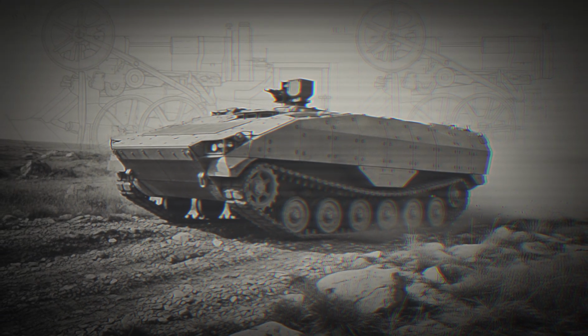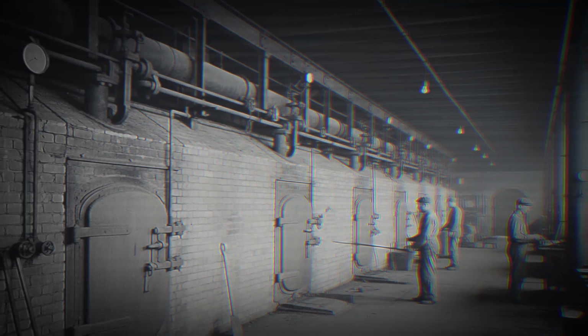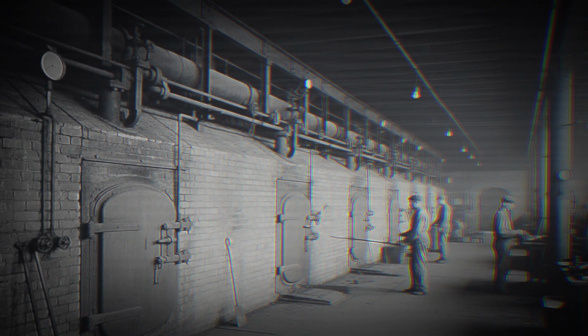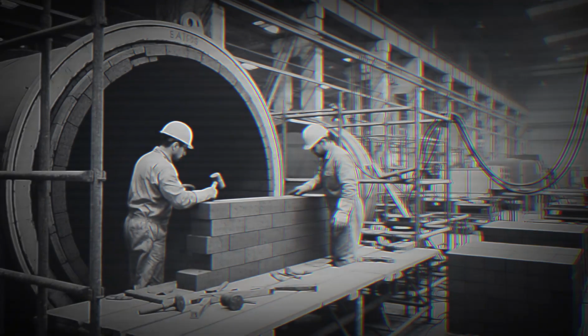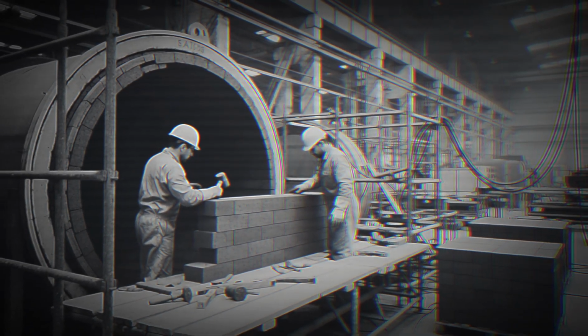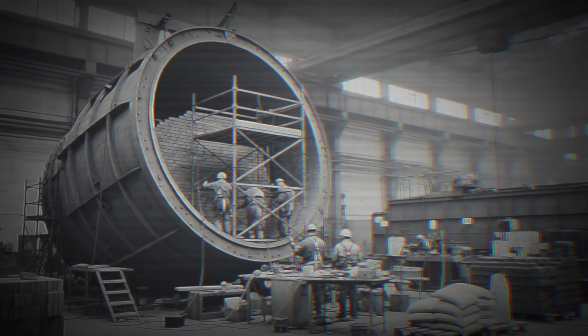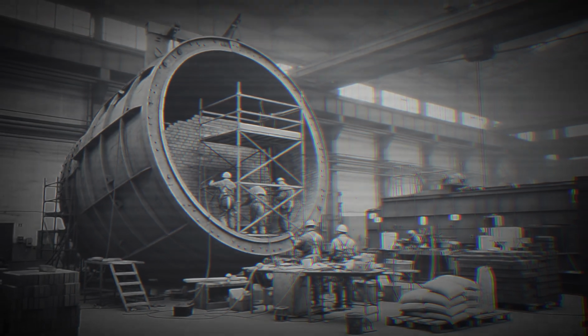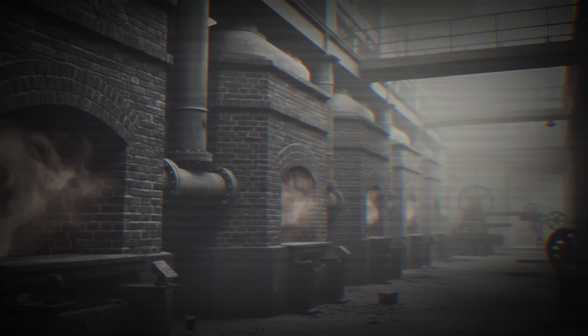But no refractory lining withstands that environment indefinitely. The slag attacks the lining chemically. The thermal cycling, heating to 1,650 degrees and then cooling during shutdown, induces cracking and spalling as the brick expands and contracts. The mechanical impact of charging solid scrap damages the surface. The tapping of liquid steel through the tap hole erodes the area around that opening with every heat. A furnace hearth in continuous operation typically required relining every 200 to 400 heats, depending on furnace design, operating practice, and the quality of the refractory brick. At 6 to 12 hours per heat, that is roughly 2,000 to 5,000 hours of operating time.